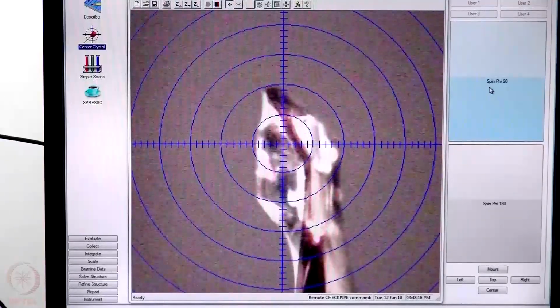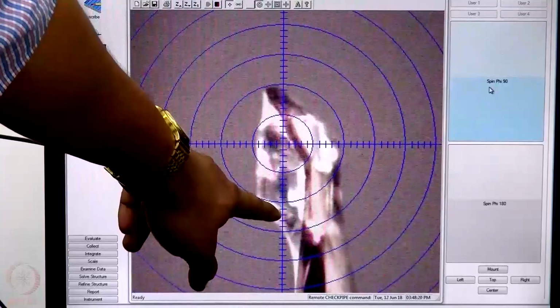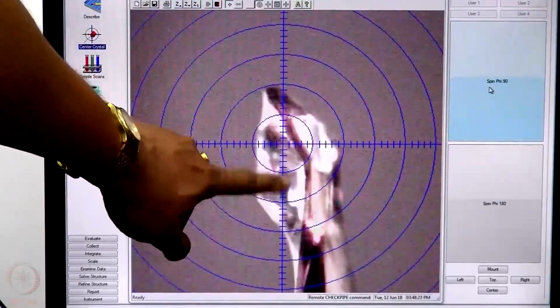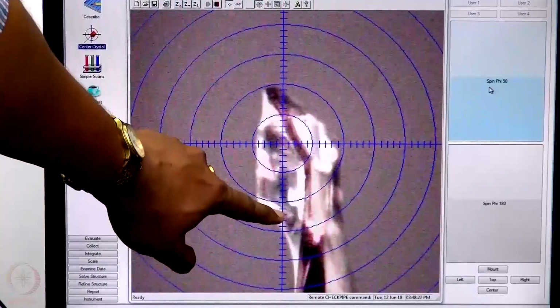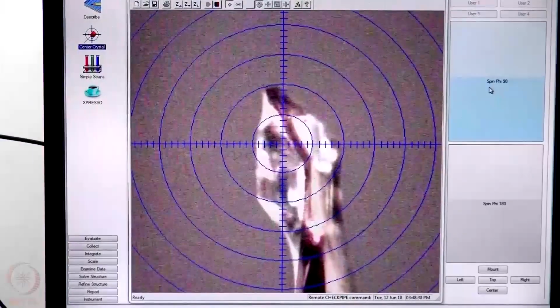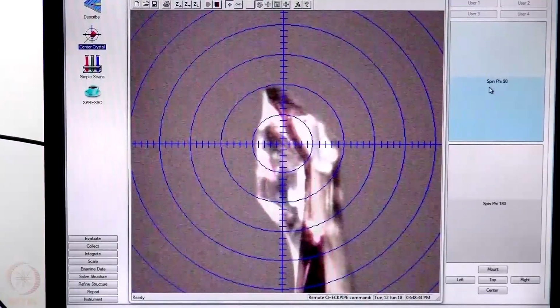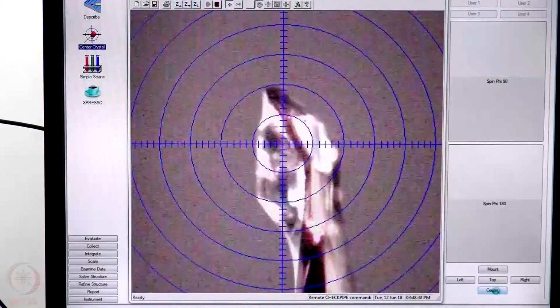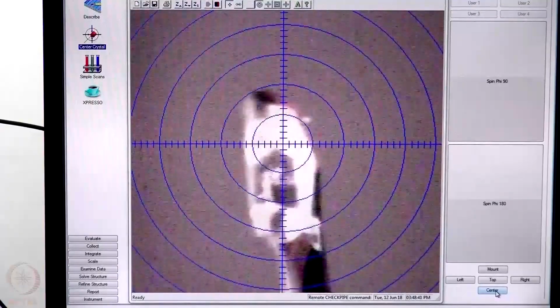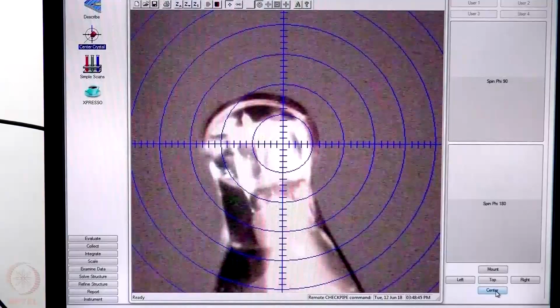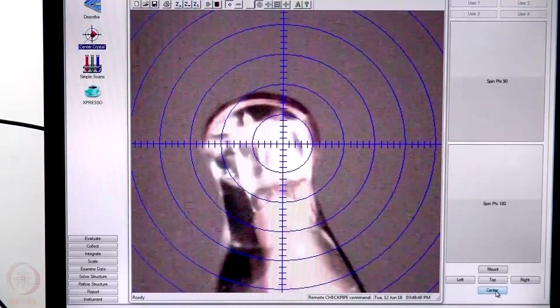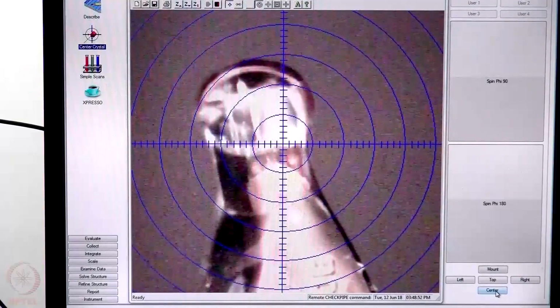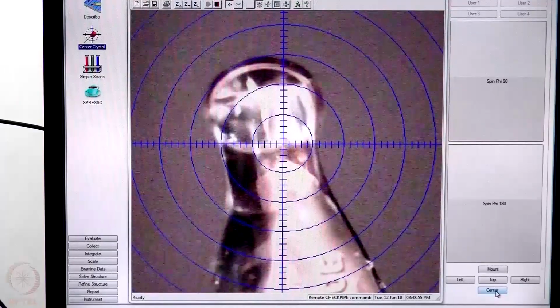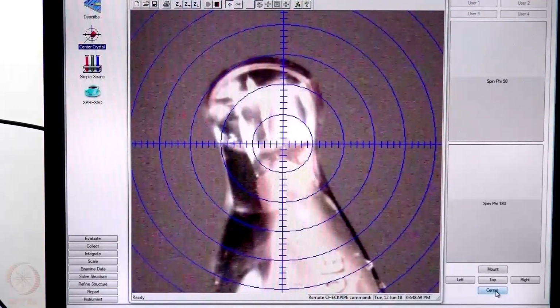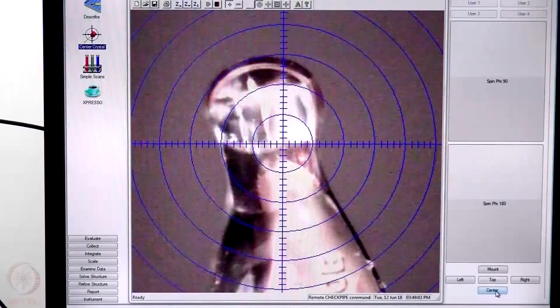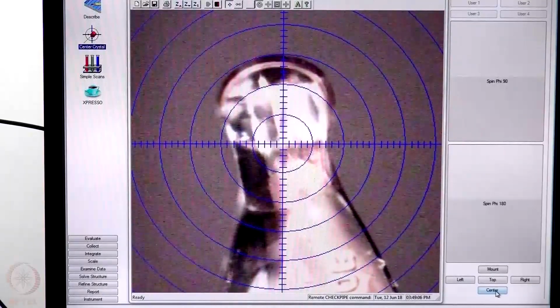So now it is sort of focused and we can see that the crystal is somewhere here to there, which means the crystal is not at the center, it is at a much lower position. So this means we need to increase the height of the crystal further. So now again we come back to the old position, increase the height of the crystal a little bit and then fix it here for the time being. And then it is not at the center, so we further bring it to the center.